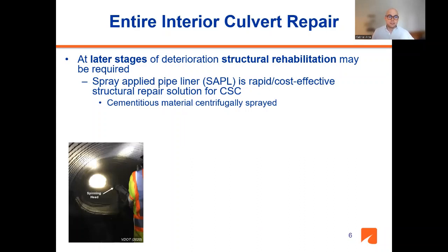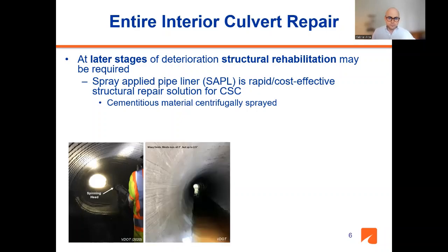As you can see in this image, this is the culvert. You have the host metallic pipe, and you use this spinning head. You pump the concrete to that spinning head, and due to the rotation of the spinning head and centrifugal forces, the material is expelled to the surface of the host pipe. And you can build a cementitious pipe inside of the host pipe. Usually a thickness of around 2 inches is used for this type of repair.